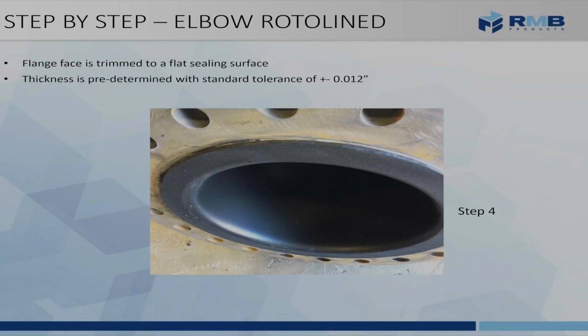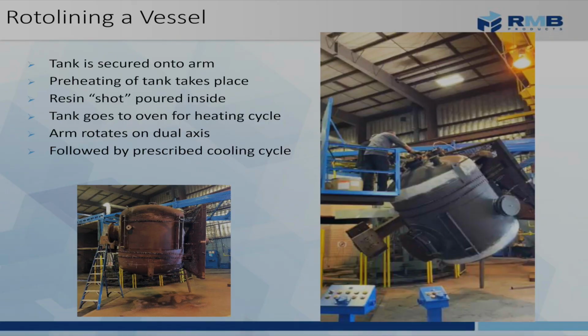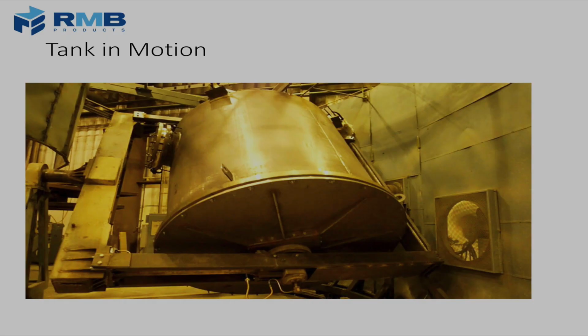Finally, we do a machine process onto the face where we make sure that it's true and flat to the specified tolerance. So there you go. So that would be a fitting. Now, in the case of a vessel, much more heavy, there's going to be more rigging. You can see this vessel rigged up onto this arm here. And in fact, I have a little video here which shows what we do.